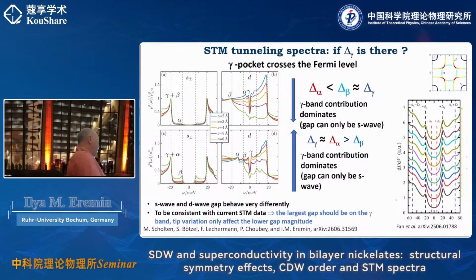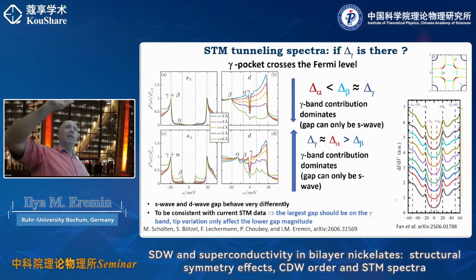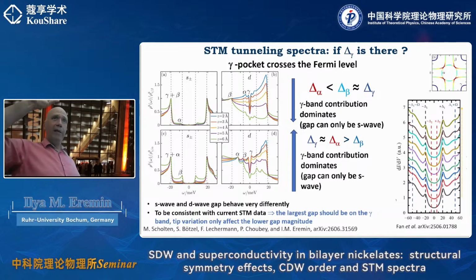And again, what we suggest is that in order to make an unambiguous confirmation, you need to do this height dependence measurement. So you need to vary the tip position and try to measure the dI/dV curve as a function of height. So that's just the first message. I have been talking to the STM groups here in China who are in a position to do this, so they are trying to do it. But of course, you need to know overall that the tunneling matrix element is exponentially dependent, so that's a very challenging experiment by itself.